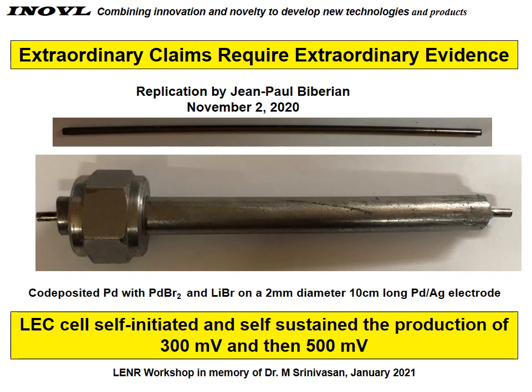One of the first questions that people ask is, has anyone else replicated our results? The answer is yes. In this replication, Jean-Paul Biberian used a 2 millimeter diameter palladium silver alloy, about 4 inches long, as the inner working electrode. He put it in a cell, filled the cell with hydrogen gas, and heated it to several hundred degrees C in order to increase diffusion of hydrogen into the metal lattice.